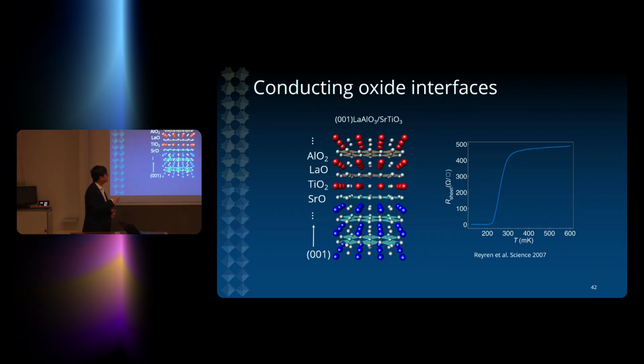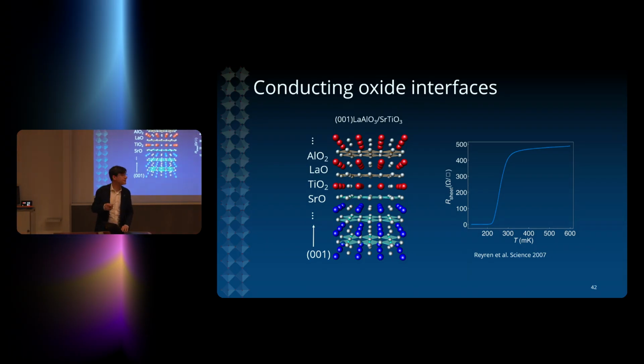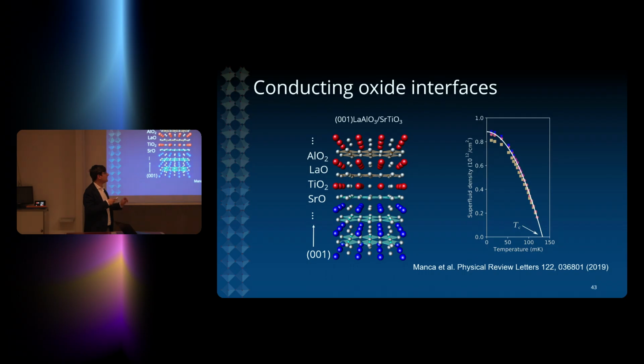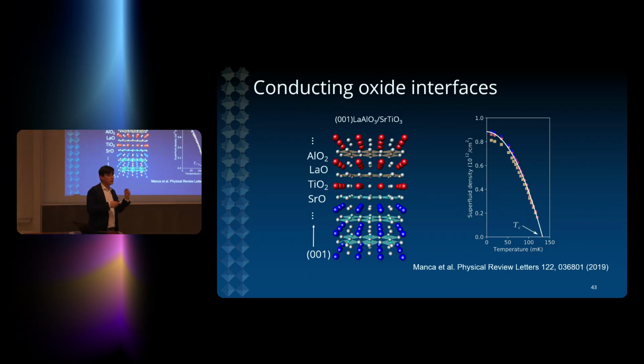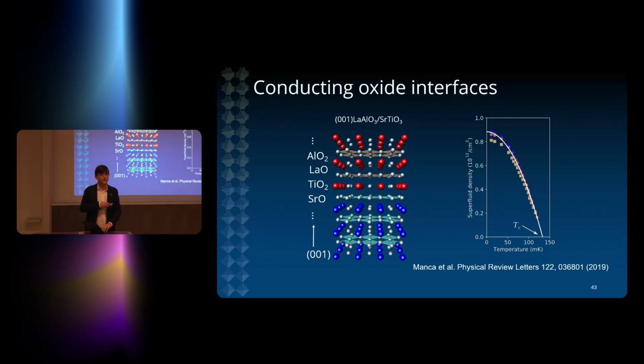And these superconductors at oxide interfaces have a lot of unusual properties. First of all, you have an extremely low concentration of Cooper pairs. We heard about Cooper pairs, the elementary actors in the world of superconductivity. In these systems, you have as few as 10^11 Cooper pairs per square centimeter. This amounts to only a few Cooper pairs per coherent volume in the system, which is a very interesting limit to study superconductivity.